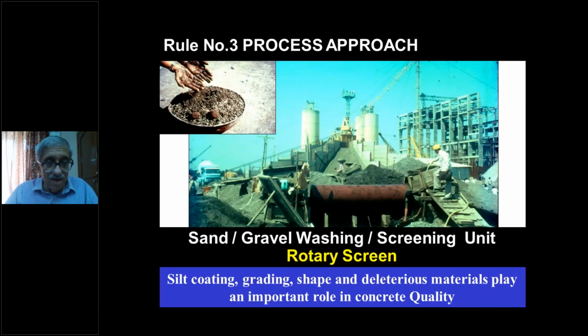Another very important thing in the process is that every ingredient which goes into the batching plant has to be of proper quality. I can give you one very good example that when we started unit number 5, the target was to do almost around 1 lakh cubic meters of concrete during the period of construction from the batching mixing plant, and not considering the other small mixers and concrete producing units that were there in the plant, far away from the main plant. So total quantity must have been about 1.5 lakh cubic meters of concrete.